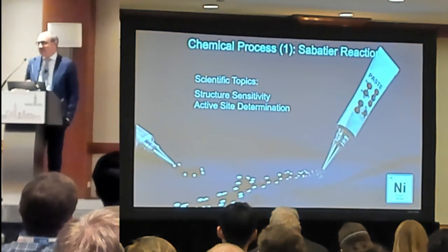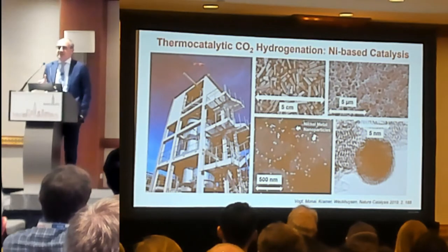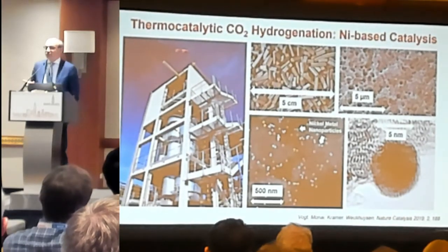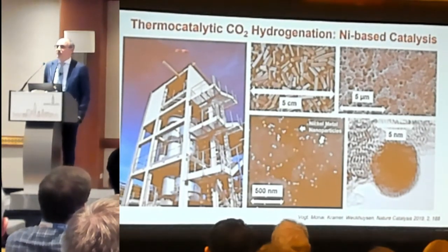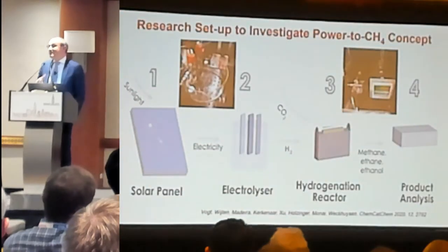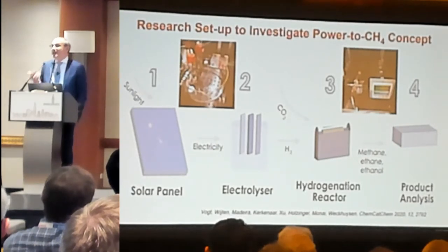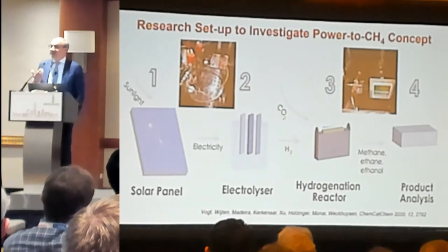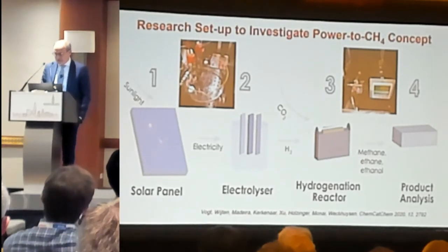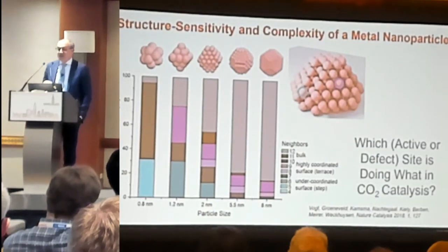Can we find some common parameters, or can we compare the differences and similarities between gas phase and liquid phase catalysis? I want to start with the Sabatier reaction, which is nickel CO2 hydrogenation. It is done with nickel-based catalysts — metal nanoparticles on different supports — put into a reactor. There is one in Germany at pilot scale. I want to focus on the concept of structure sensitivity: when you change a metal nanoparticle you change the surface, and when you change the surface you expose different atoms to the molecule.